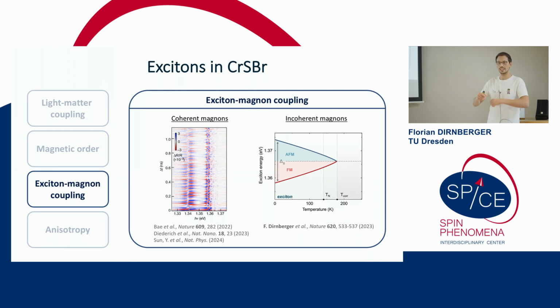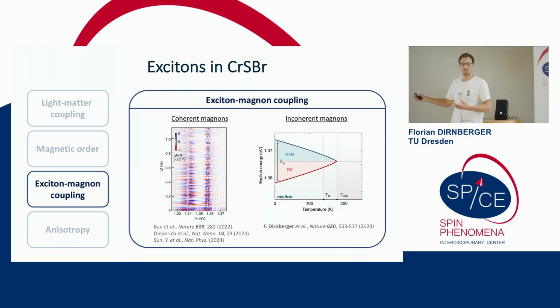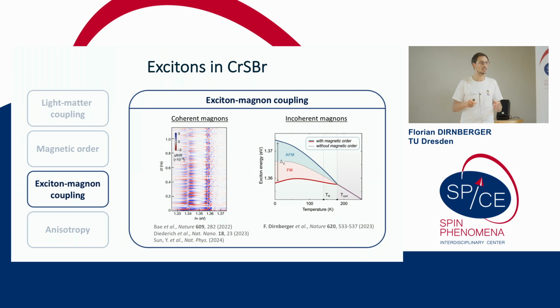In this model, we figure out the math of the angles and so on. You find that if your crystal is in an antiferromagnetic phase and you increase temperature, which means that you incoherently start to induce thermal fluctuations of the spin, you get a redshift of the exciton as a function of temperature. But if you force the magnetic order into a ferromagnetic configuration and then let the spins fluctuate, this will actually lead to a blue shift of the exciton. This is a prediction that we made based on a model. Then we realized that to compare it to the experiment, we have to include the phonons. We end up with a model prediction that looks like that.